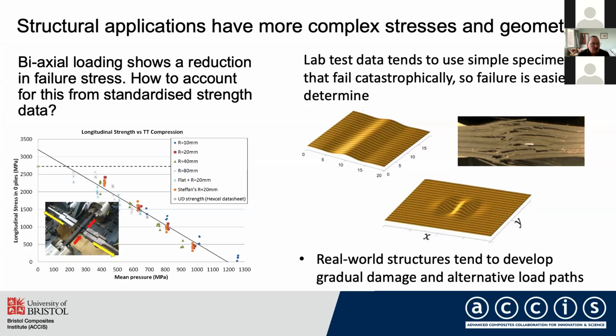And what you see is that the measured longitudinal stress in the material drops off with the applied pressure. So again, we need to not only understand the local damage interactions at play, but also the multi-axial stress state. And finally, I want to just look at the geometric effect, again, as we go up the length scale.